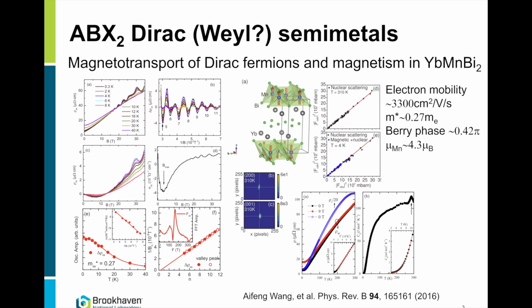And so the first surprising observation: these are very good metals, very low density metals. You can see quantum oscillations, at several kelvins to 10 kelvins temperature, indicative of light Dirac electrons with non-trivial Berry phase. At the same time, the magnetic layers carry very large ordered moments. This is magnetic refinement of the magnetic structure, just to show that it's perfect. This is a heat capacity showing that the magnetic layers order at around room temperature in this particular material and carry a 4 Bohr magneton magnetic moment.